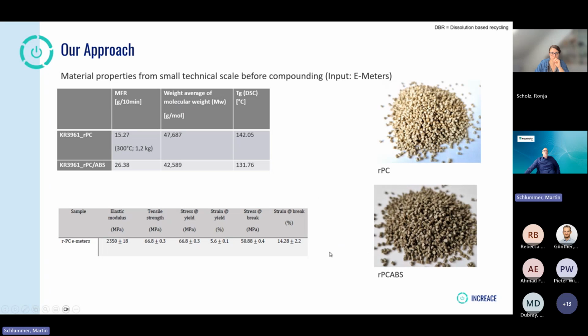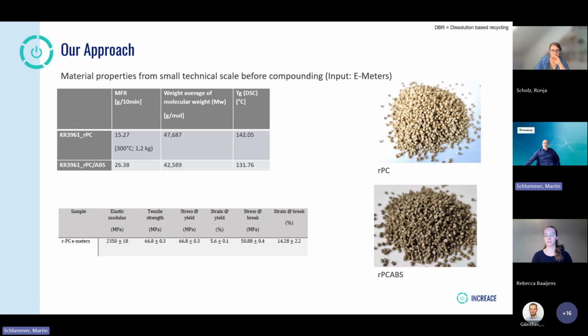Finally, let's look into material properties. And let me please point out, this is not the one which is considered to be sent out to industry. This is before compounding, very important, since we did not only reduce the levels of flame retardants, so we may, of course, also have an effect on any other additives in there. So in the end, it is for us not surprising that the MFRs are probably a bit higher than usual. The average molecular weight distribution is still fine for us, and the Tg are also still where we expect them.